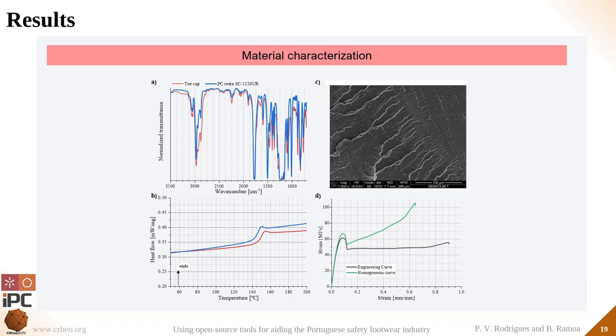One we used was the differential scanning calorimetry to identify the glass transition of the material. As you can see in the plot of image B, the glass transition of both materials are quite close to each other, and it is expected that, unless they are exactly the same material, there will be some shift in the glass transition. This again allows us, given the information that we had before, to corroborate that this was in fact a polycarbonate.